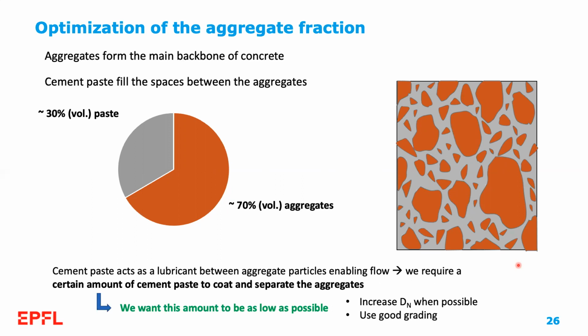So we need a certain amount of paste, but we want this amount to be as low as possible. There are basically two things at the aggregate scale that we can do to achieve this. We can increase the maximum aggregate size when possible, and we tend to use the largest aggregate sizes we can, and design our structure to enable this if possible. And also we need to use good grading of aggregates.